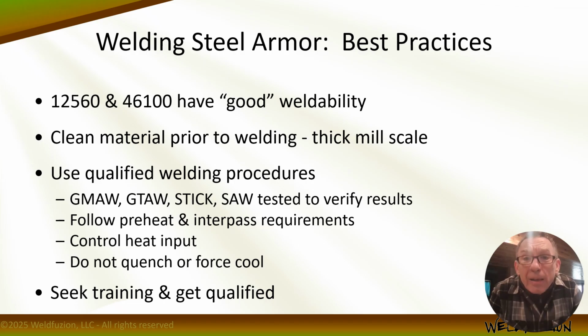As a result, heat input is extremely important, and we're not only referring to pre and post heating, but also to process heat input in terms of energy over a given distance, right? So kilojoules per inch of weld, and that takes into account not only amperage and voltage, but travel speed. So if we sit there at a lower current level and it takes longer to make the weld, we could be doing more damage than if we used higher currents and traveled faster.